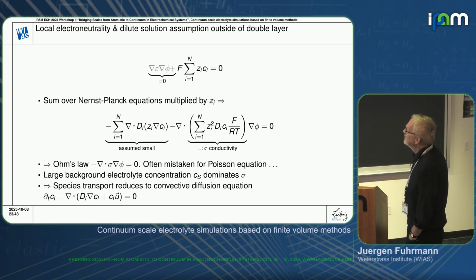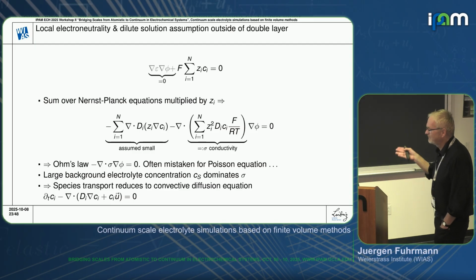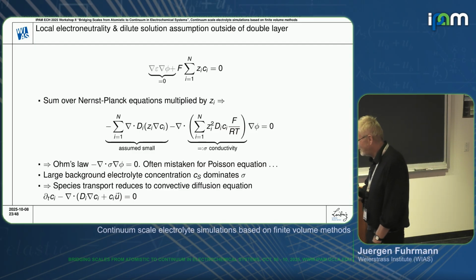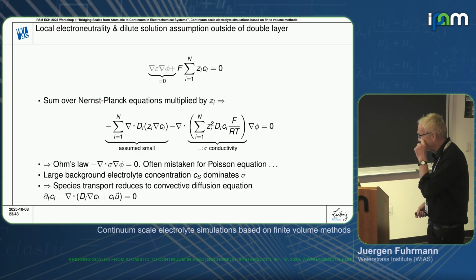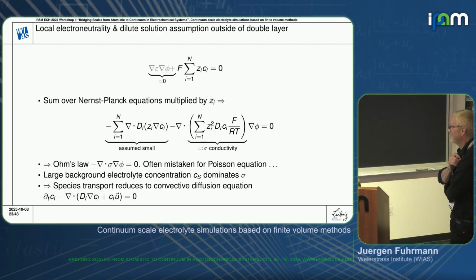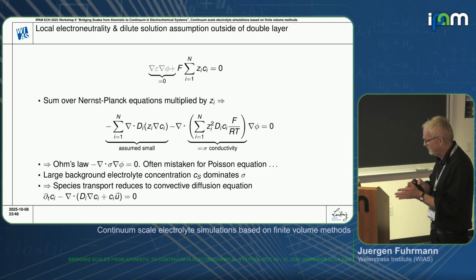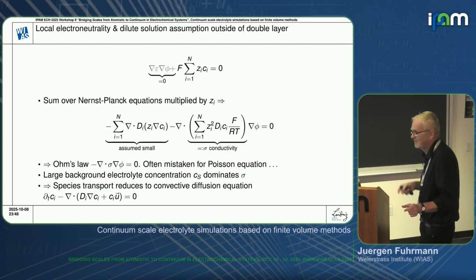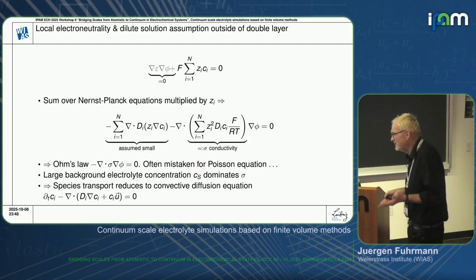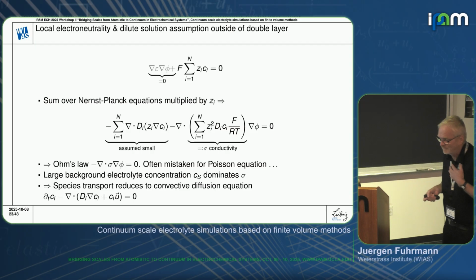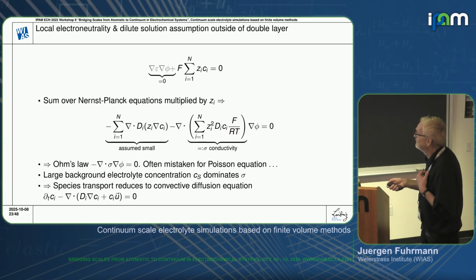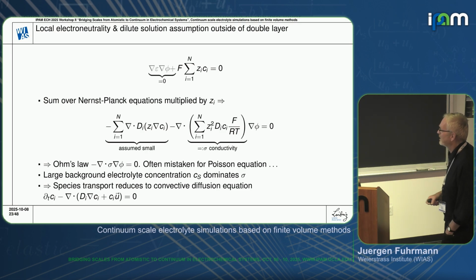Nernst-Planck equation. But then, of course, if we look at the sizes of experimental devices which electrochemists use, then basically this is at a size where everything which is happening in our polarization boundary layer is happening on a spatial scale which is much smaller than the device width. So it's nearly impossible to take this into account if one wants to solve this numerically. So people basically work with the assumption of local electroneutrality. And this means that our Poisson equation turns into just an algebraic equation.